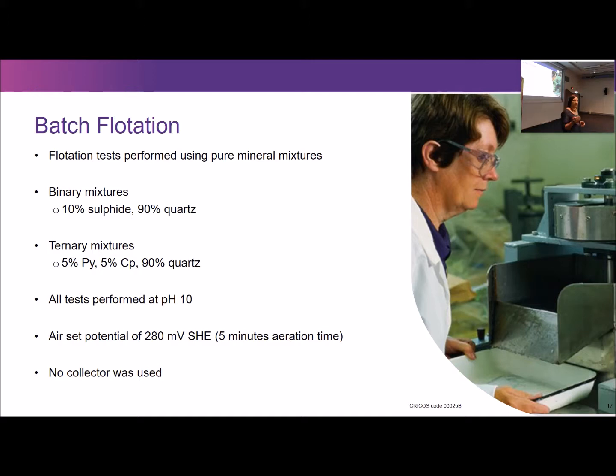All tests were done at pH 10 at an air set potential of 280 millivolts, and this was just done by aerating the pulp for 5 minutes, but that potential was then maintained throughout the test using chemical additives, so it never varied. And we used no collector because we wanted a nice clean system.